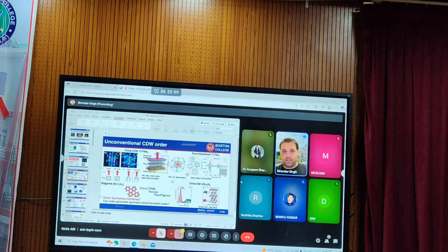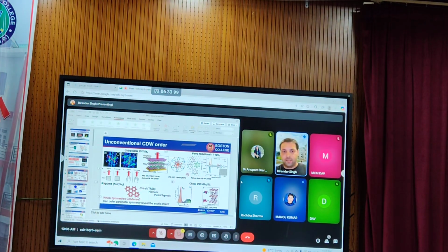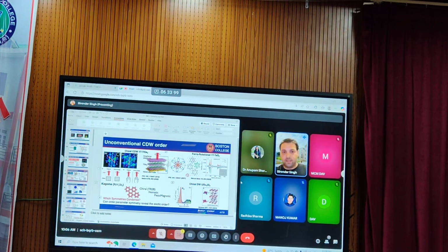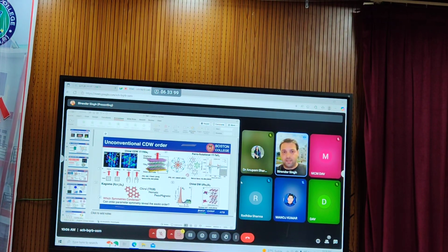You see there are different phonon modes. Some of them are quite sharp, but this first one at low energy is quite broad. This is the CDW amplitude mode or Higgs mode. The others are folded phonon modes, because the CDW makes a superlattice and that can fold the zone boundary back to the gamma point and produce new modes in the Raman spectra.